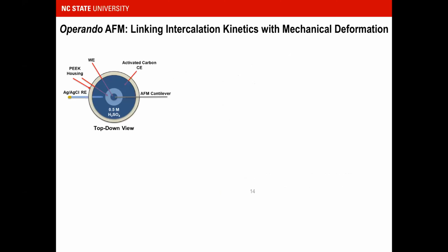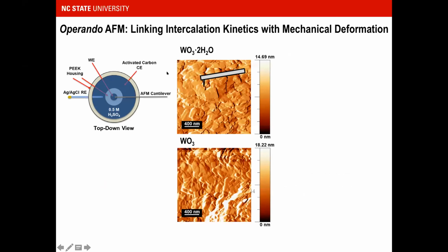And this is where our collaboration with Oak Ridge National Lab came in. They have the setup to do this operando atomic force microscopy, where we're going to link the kinetics of the intercalation that we measure from things like cyclic voltammetry with the mechanical deformation of the material. And this is how the electrochemical cell looks like. And what we're doing is, this is now topographic images of our oxide electrodes, is we're going to take the AFM tip and place it on top of our material, and then just watch the deflection of that AFM tip as protons cycle in and out.